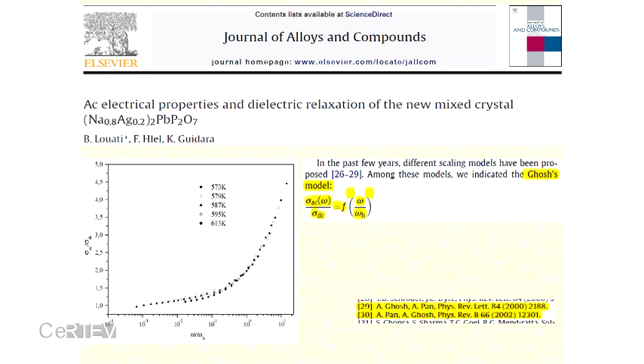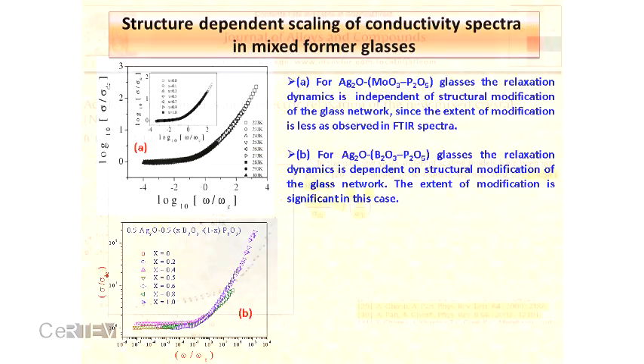I have shown here the mixed former effect glasses. You can see that there is perfect superposition for temperature as well as for composition. I am changing the silver ion, molybdenum oxide and phosphorus oxide, and as a function of temperature it is perfect superposition. As a function of composition it is also perfect superposition.